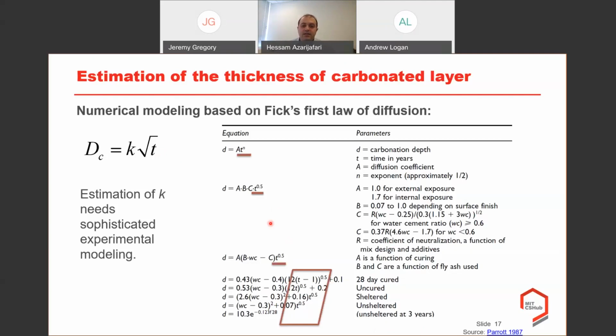So we have t to the power of 0.5, which is square root of t, and there are some differences in the estimation of the k value, because the researchers observed that k depends on multiple criteria, as we discussed earlier. The exposure condition, as you can see, some of them propose a different equation for sheltered or unsheltered concrete exposure condition, or for example, the water cement ratio is another thing that concrete researchers have put some difference on for the estimation of the k value. But what is important is estimation of k needs sophisticated experimental modeling.